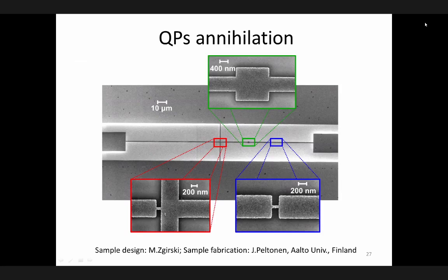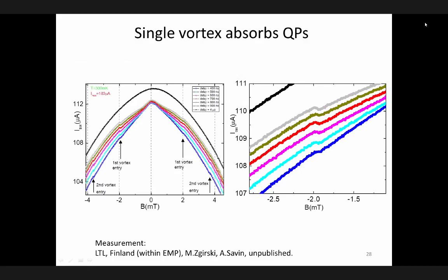So what we see, let's first do without any heating. We measure the magnetic field response, the switching current response of the bridge to magnetic field. This is the black curve. No features, this is a parabola. So this is the indication of the Meissner state. The switching current of the bridge is suppressed due to the still increasing value of Meissner currents in the vicinity of the bridge, which suppress the superconducting order parameter.